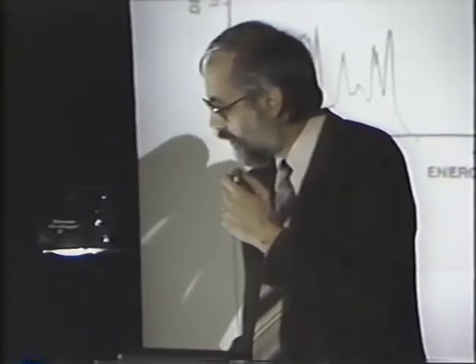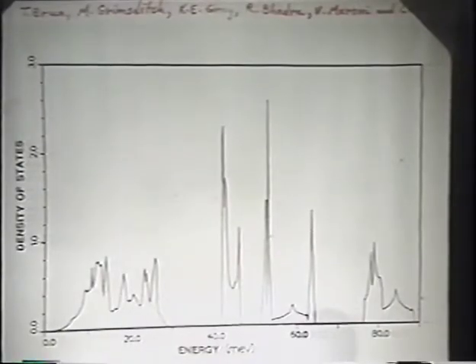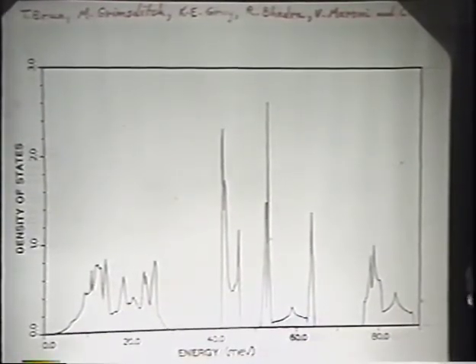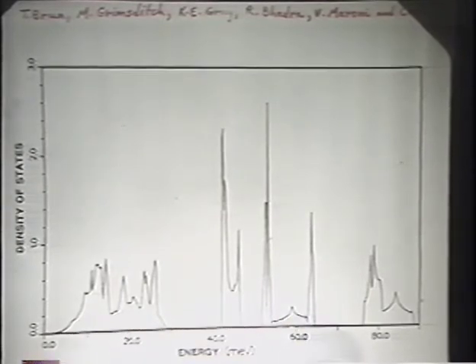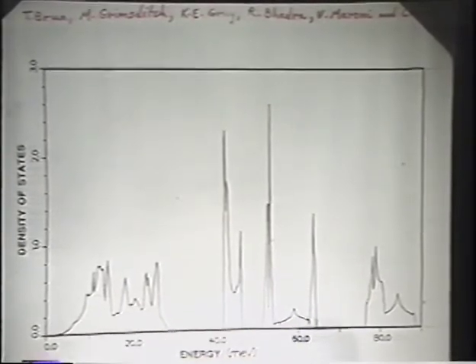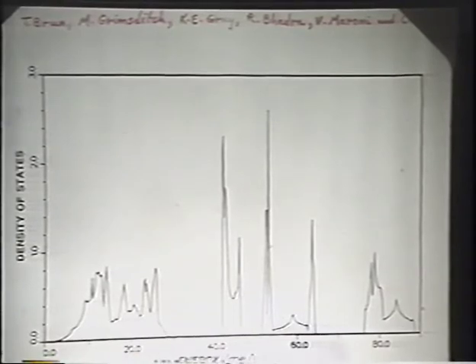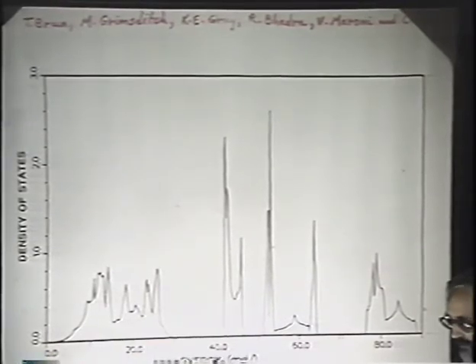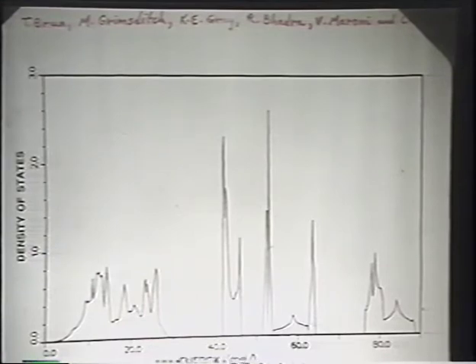We also have phonon data. Here is a phonon density of states. This is a somewhat moving target because the data is still coming along and being analyzed, but this is the result of taking some Raman data, some IR data, some inelastic neutron scattering data, and a Born-von Karman type calculation and cranking all of it together. This will certainly allow us to try to get somewhere in evaluating how good the electron-phonon interactions may be.